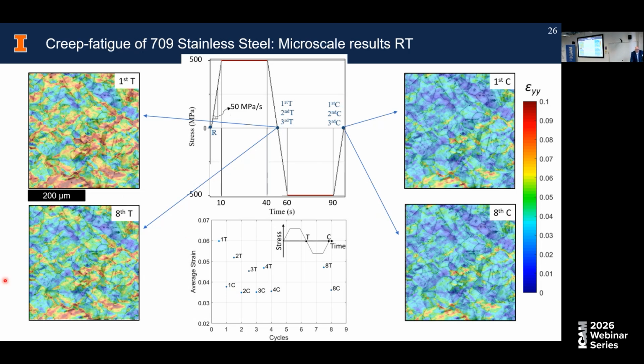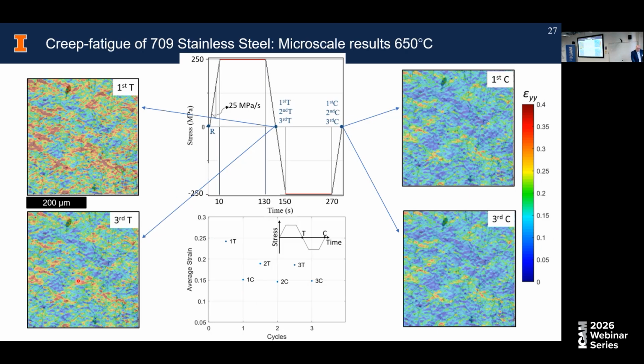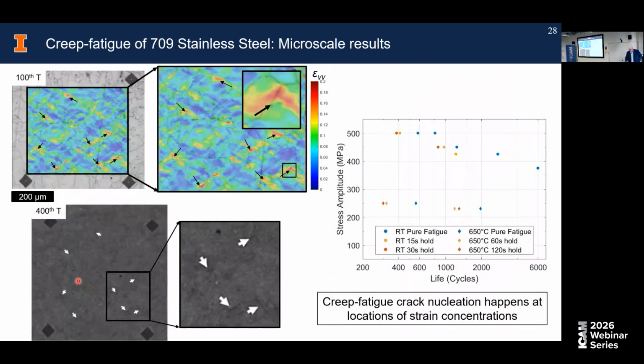And what you see, again, is that these are very similar. So again, we see the strain just accumulating at the same locations as we saw before. This is at room temperature, and same thing at high temperature. I won't stay with this too long.